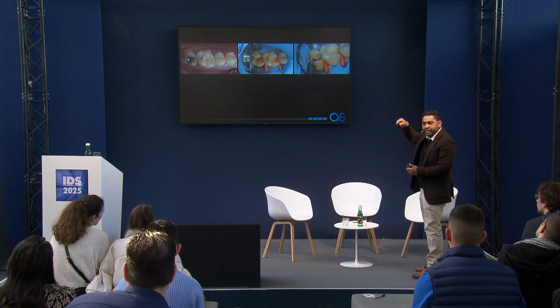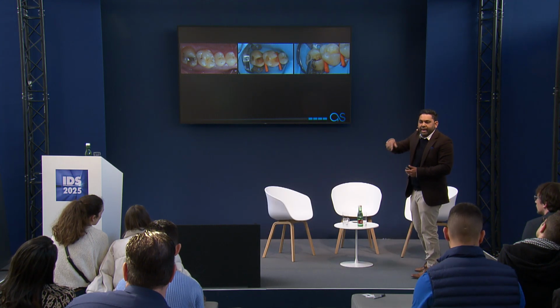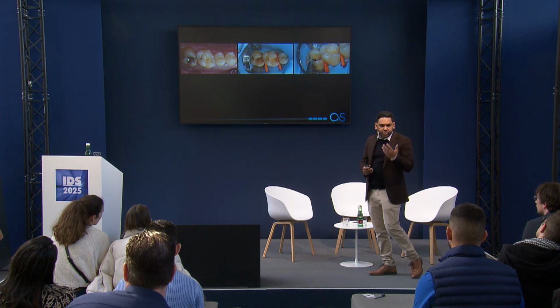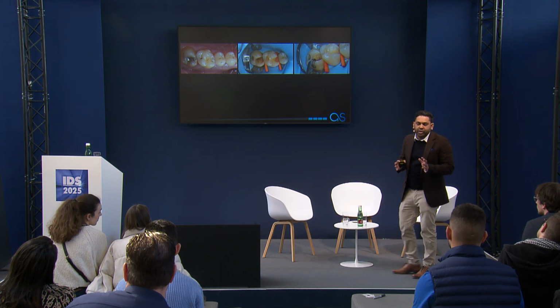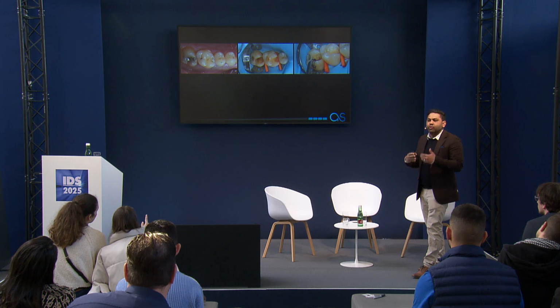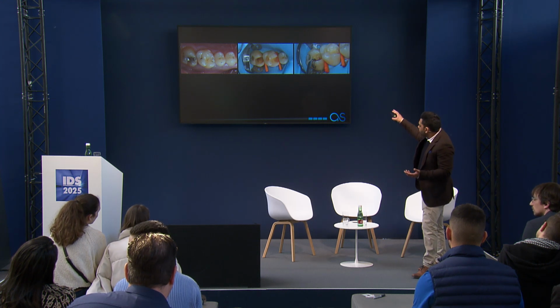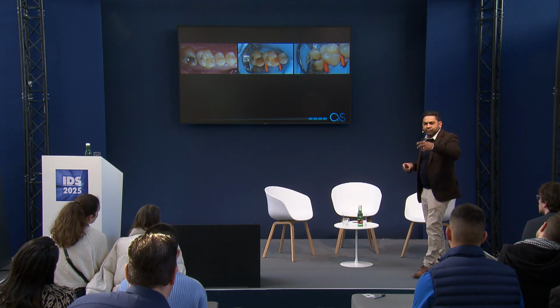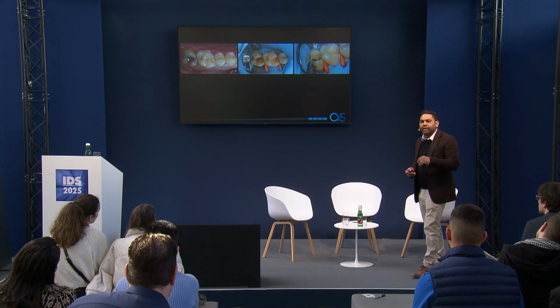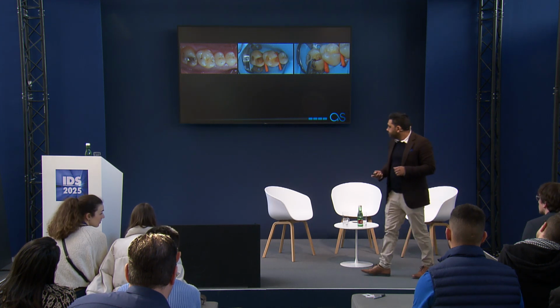And effectively, if we're placing the instrument and the width of the cusp is less than 2 millimeters, this slot within the instrument slides right down. That tells us maybe we don't have the best structural integrity, and we would consider going with an indirect composite or an indirect restoration long term. The instrument didn't go down, so I was confident we had good structural integrity. We're unlikely to get fracture of that cusp.